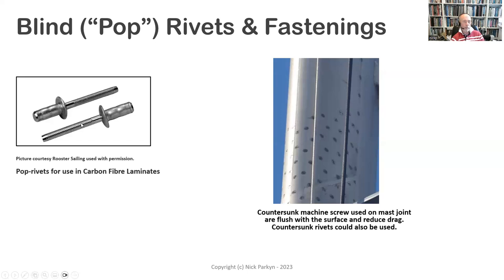So these particular rivets are done in such a way that they don't actually provide that much compressive force as you pull them up, and they also pull up to a much larger kind of ball on the inside surface. But again, they are only used for fitting some smaller types of fittings, typically things like tillers and tiller extensions. They're not typically used to attach any fittings of high load application to carbon fiber masts. But just an interesting fact that these things are available and have been especially manufactured for that type of approach.